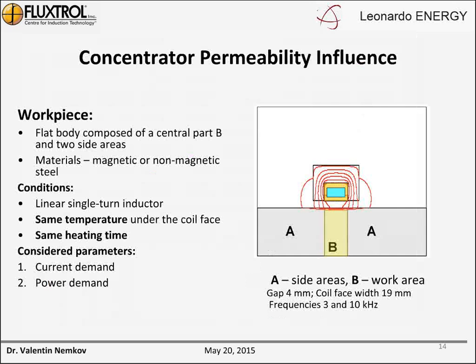Talking about permeability, we immediately must ask a question. If the permeability of a material is, for example, 20, how can it work and compete with laminations that can have permeability, let's say, 500? We made a special study using computer simulation. The single-turn coil had a C-shaped concentrator, and the load was a plate with three areas. One is area B under the coil face, where we want to have constant power required for the real technological effect. And we have two areas A, which are the side areas.